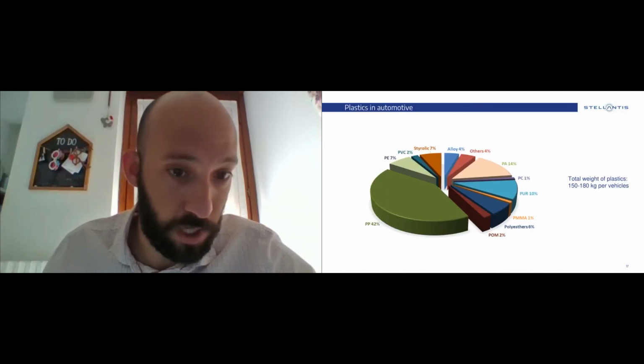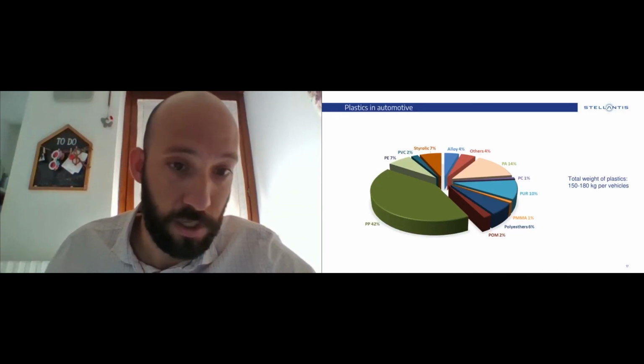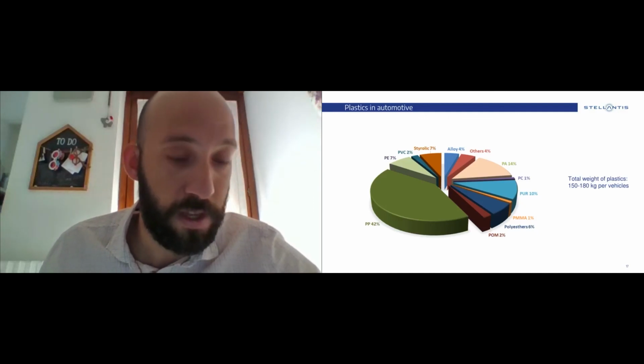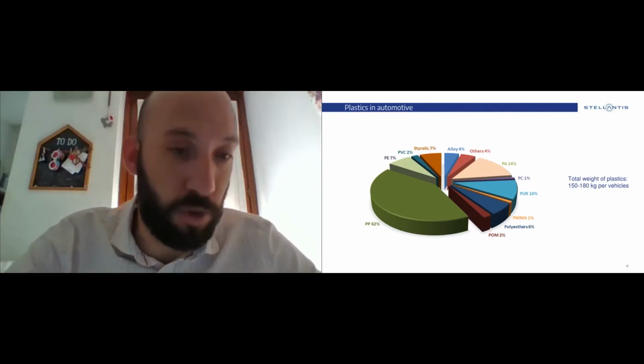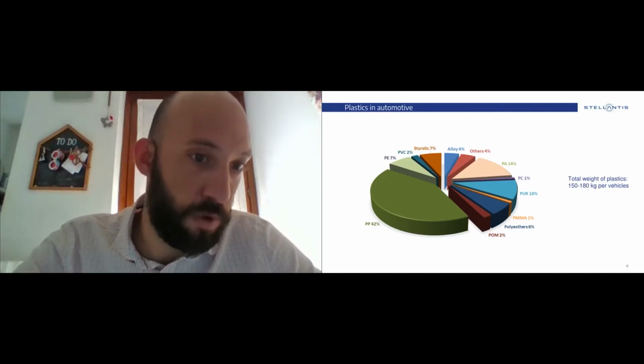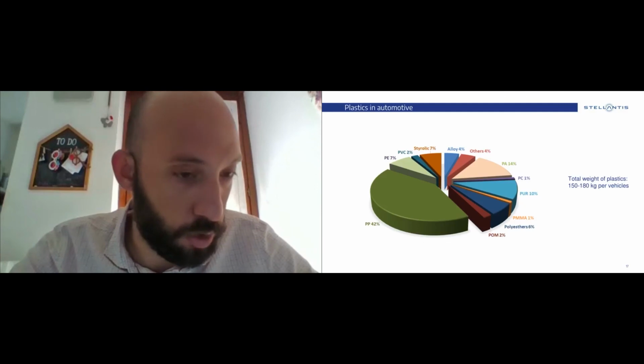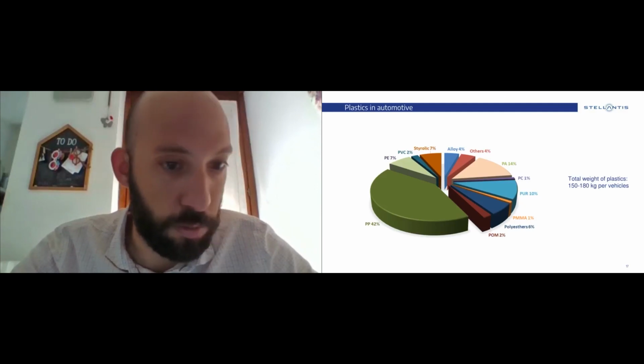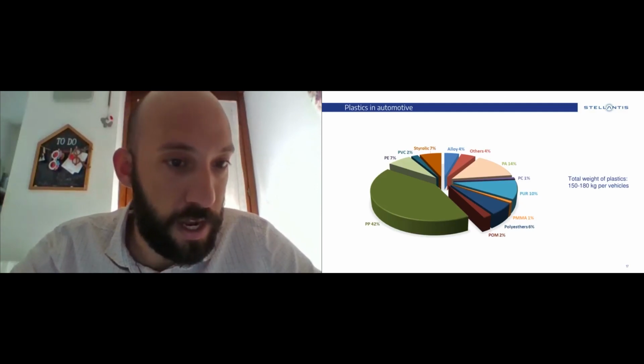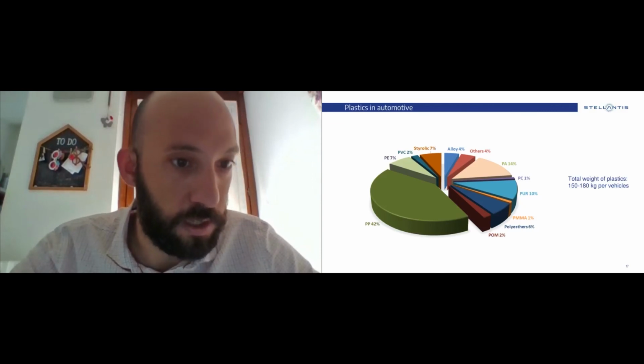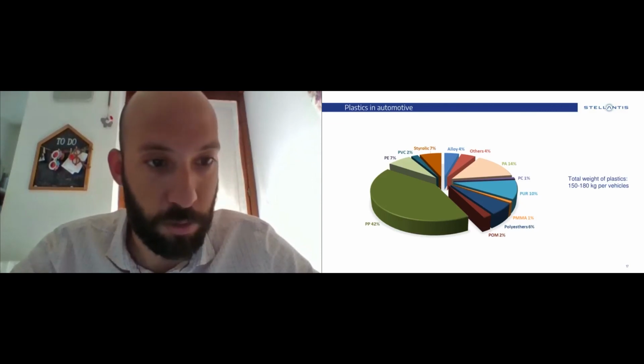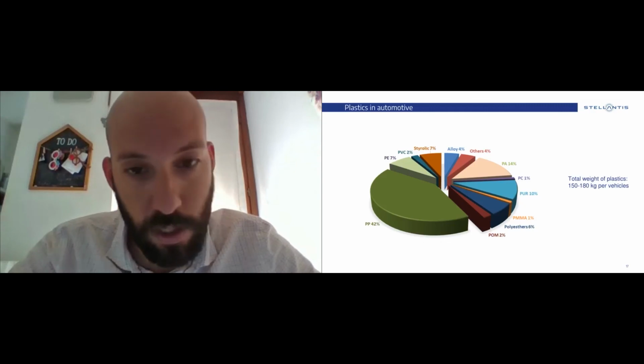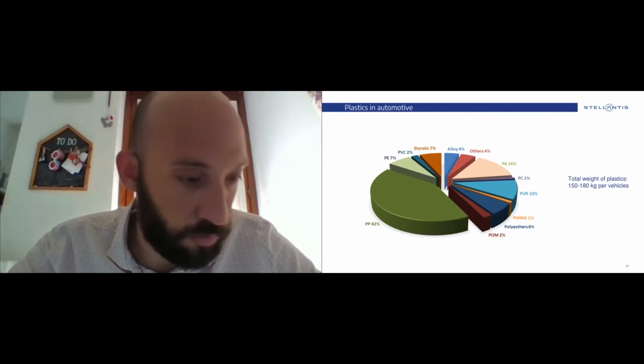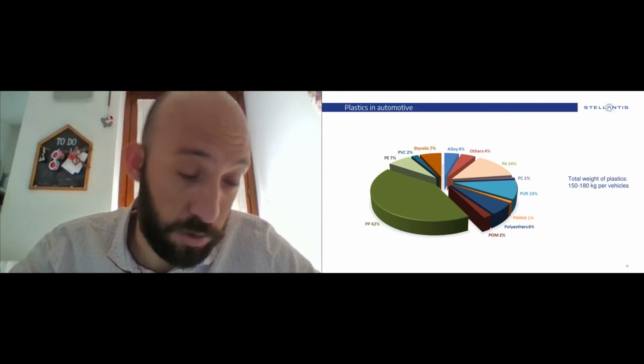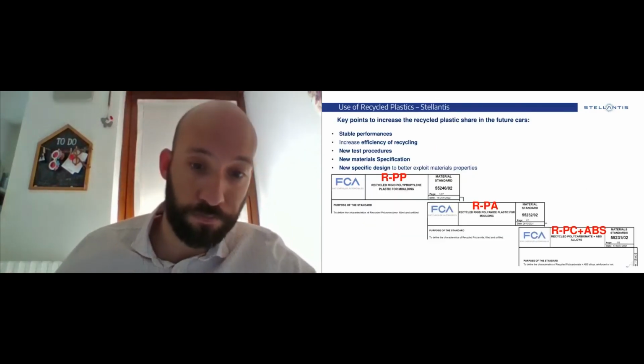So in the graph here, I report more or less the plastic share in the automotive, where up to 100 kilograms of plastics per vehicle, we have more or less 50% covered by polyolefin, like polypropylene and polyethylene. And then with polyamide and the styrolic alloy, so polycarbonate and polycarbonate ABS, we are around 90% of the total plastic share, thermoplastic share in the car.